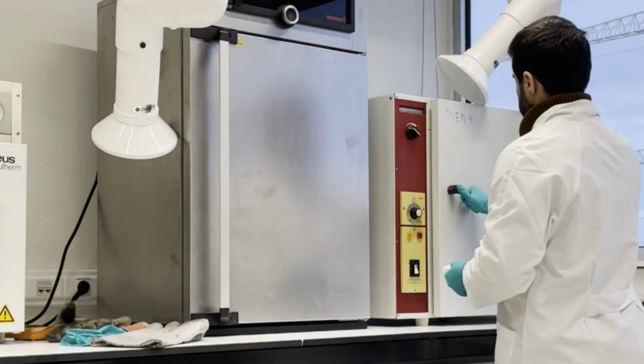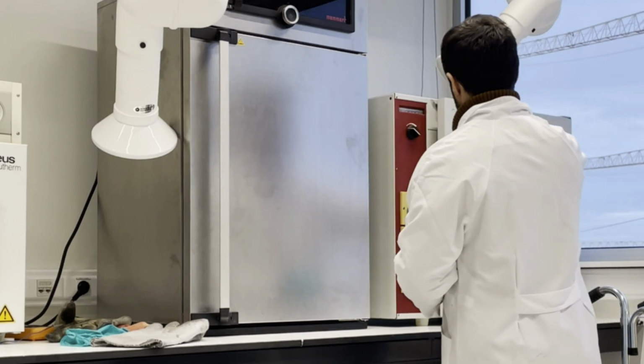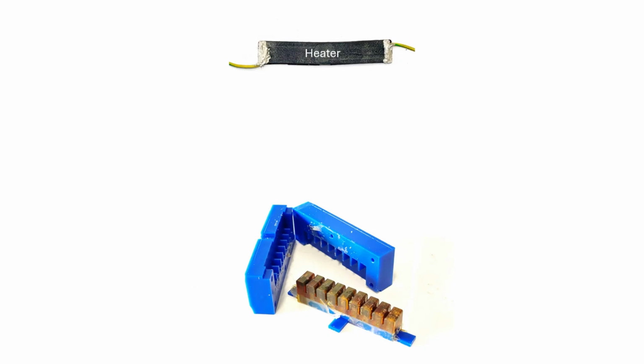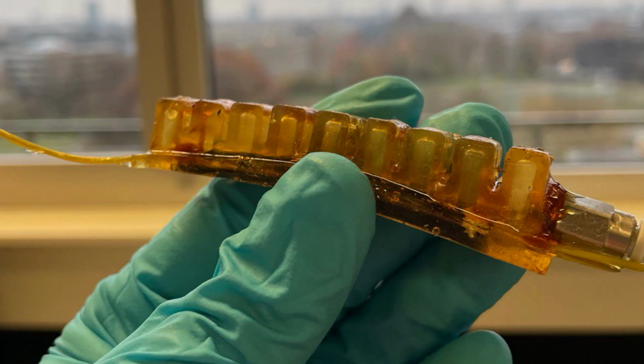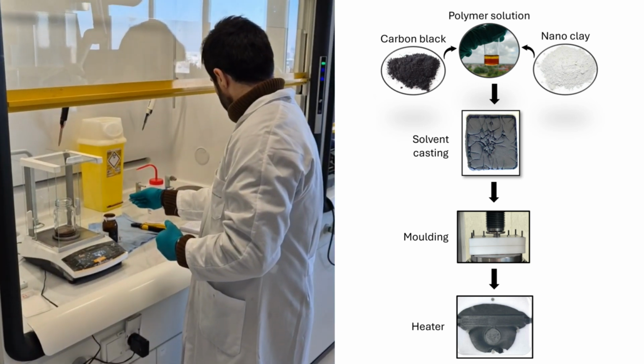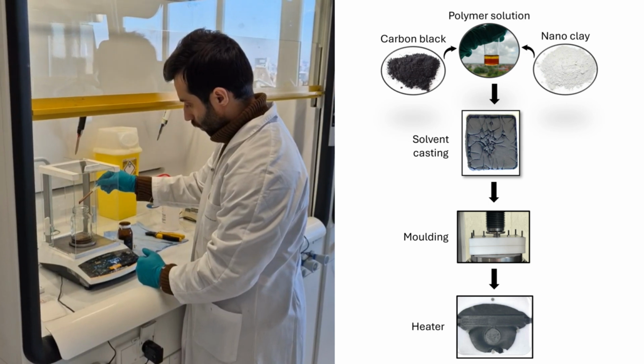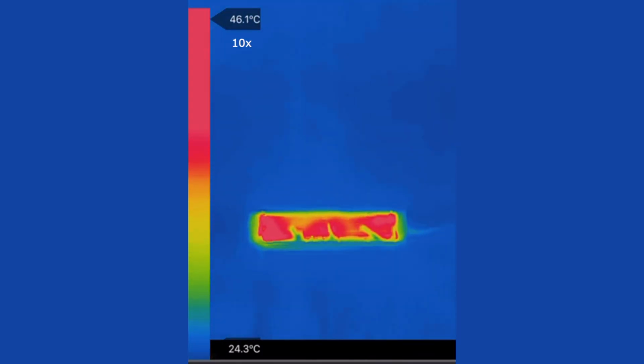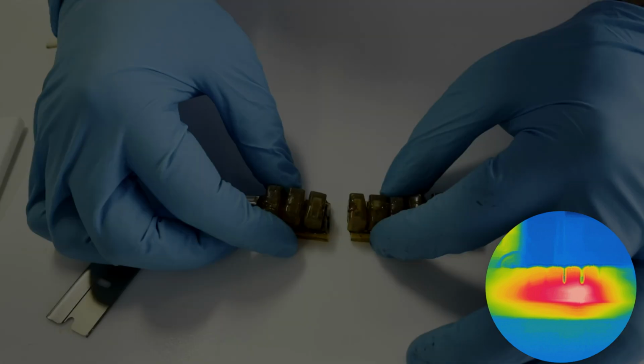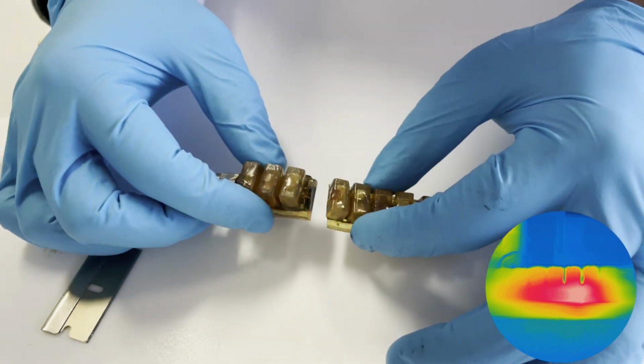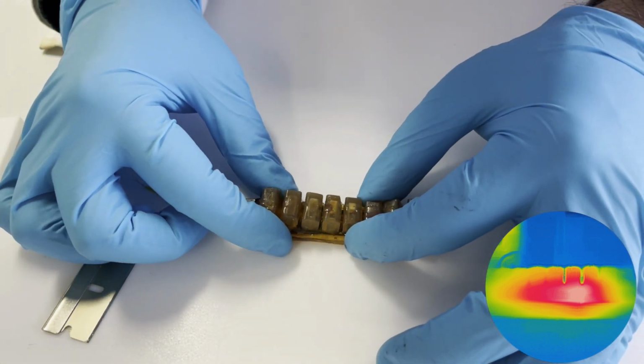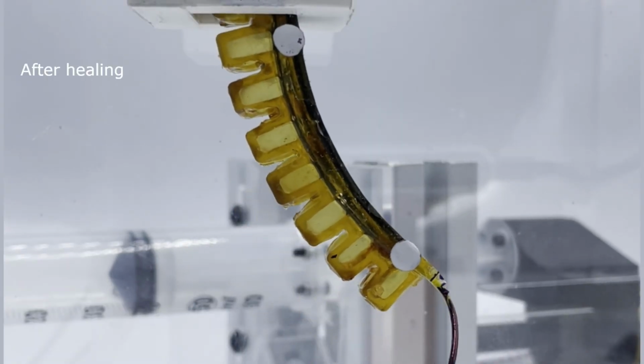After damage detection and closing the gap, the next phase is stimulating the material for the actual healing, often by increasing its temperature. Previously, this was done using external ovens, which are bulky and require heating the entire robot. My solution was to innovate a self-healing heater that can be embedded directly into soft robots, enabling localized heating. This was achieved using conductive self-healing materials, similar to the materials used to make the damage detection sensor. I developed a thin film of this material that generates heat via Joule effect when electrical current passes through it. Moreover, when the heater is damaged, the resistance is locally increased, so the heat is naturally concentrated at the damaged area, providing localized heating and healing.